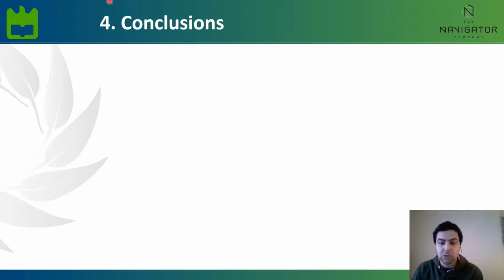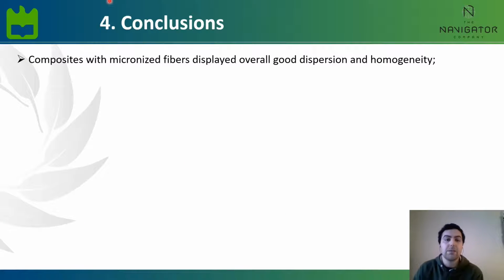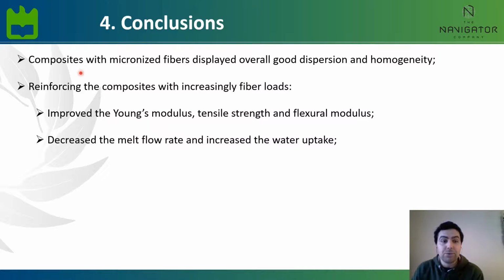Now moving on to some conclusions of this work. From this work we can conclude that composites with micronized fibers displayed overall good dispersion and homogeneity, and that reinforcing the composites with increasing fiber load of micronized fibers led to an improved Young's modulus, tensile strength and flexural modulus, but on the negative side led to a decrease in the melt flow rate and an increase in the water uptake capacity.